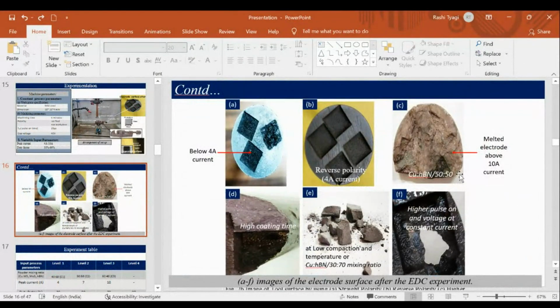So this is the process by which we have selected the process parameters. Below 4 ampere current, there is no deposition. When we increase the current, deposition takes place. Also the electrode melted above 10 ampere current, it means when we increase the current above 10 ampere, the electrode melted. Also at high coating time, a hollow structure is obtained.